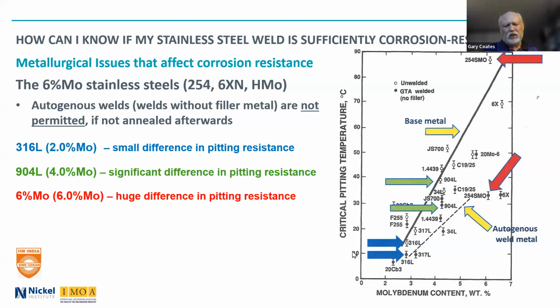the critical pitting temperature. The higher the number, the more pitting resistant it is. In the bottom, the horizontal axis is the molybdenum content. So the solid line pointed to by the yellow arrow is the base material, the parent material, where the dotted line is the autogenous weld metal. And you can see with 316L, there's a small difference in pitting resistance, generally not a huge effect there. So generally you weld 316L in environments that may cause minor amounts of pitting with 316L filler metal.